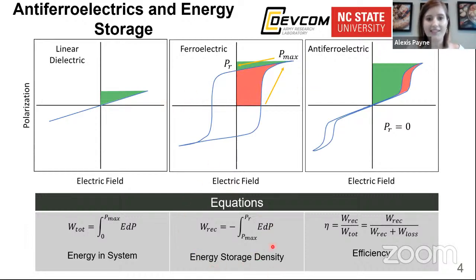When thinking of these three in terms of energy storage, we have to go to the equation for energy storage density, which can be found in the bottom center of this slide. It is denoted by the green region in each of these plots. So more green is good. It's a higher energy storage density. The red region in each of these plots is energy lost. So more red is bad. Hopefully you'd agree with me if I asked you which of these you would use for energy storage. You'd also pick the antiferroelectric. And that's because it has a max polarization much higher than that of a linear dielectric, but it's not nearly as lossy as that of a ferroelectric.